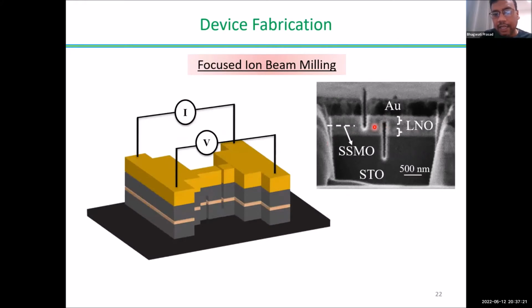So what will happen? We basically apply the current from the two electrode pads and then measure the voltage. The current is passing through here, and the voltage that we are measuring is the voltage drop across here. Since the gold and lanthanum nickelate are metals, whatever voltage drop we see is significantly coming from the one dropping across the barrier here.